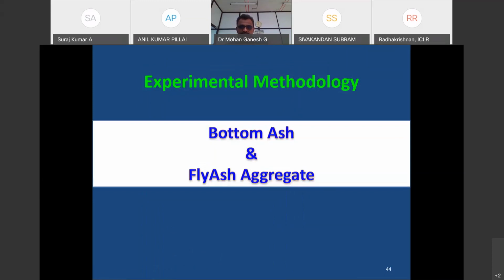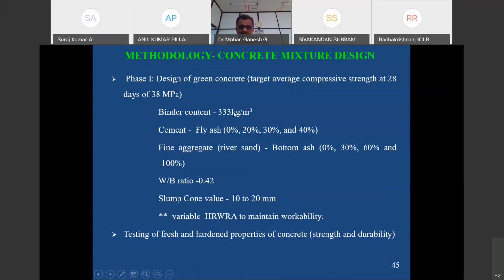Now I want to go to the bottom ash as well as fly ash aggregate. Here, we have done the mix design with a low binder content, 333 kg per meter cube. Simultaneously, cement is replaced with 0%, 20%, 30% or 40% of fly ash. And parallelly, we have replaced the fine aggregate with bottom ash, which we obtained from the Neyveli Lignite Corporation. We replaced fine aggregate by 0, 30, 60, and even 100%. So in that case, we did not use any fine aggregate at all, only bottom ash. For comparison purposes, we have maintained a constant binder content, and slump values of 10 to 20 mm. Here we have used high range water reducing admixtures, the superplasticizer.